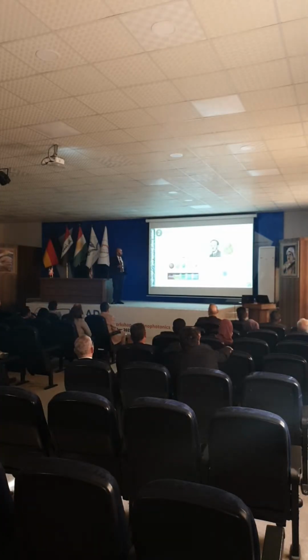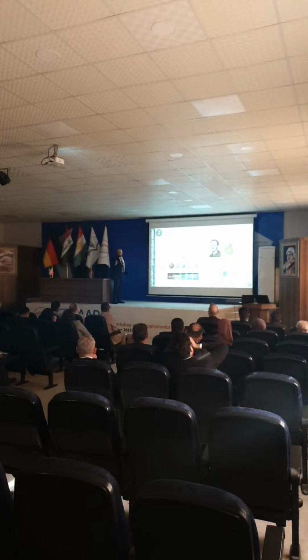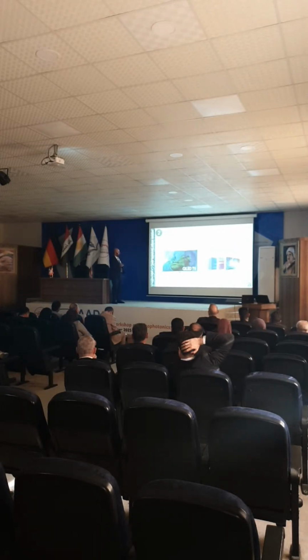Also, there is another property we call quantum confinement, and this will be dominant when the size of the nanoparticle is comparable with the de Broglie wavelength. And this is very important, especially for oxide nanomaterials. So this is the case of the band gap. When you have a band gap, it's not like a bulk material. In bulk material, you have a fixed band gap. But in nanoscience, the band gap will be a function of the size. So we call it tuning the band gap. Whenever you change the size of the nanoparticle, you are changing the band gap precisely.